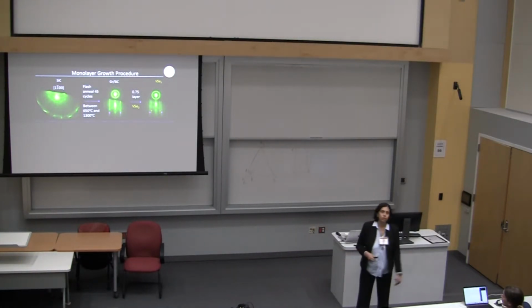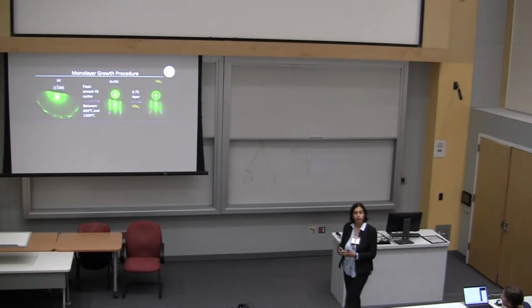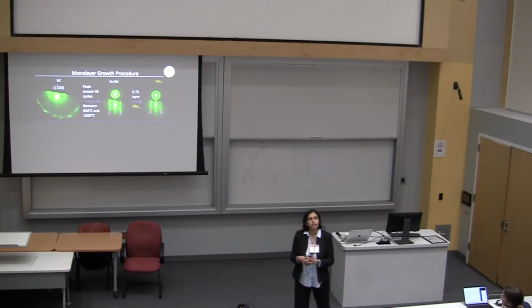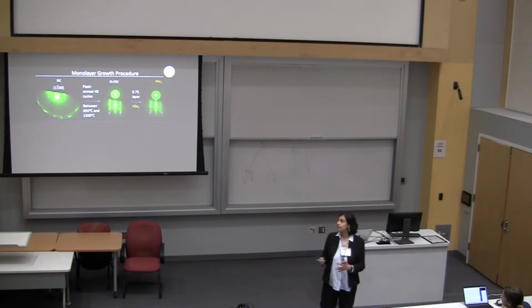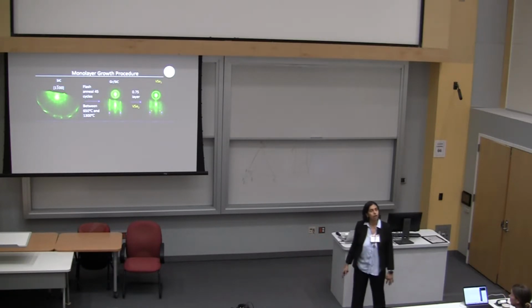So let me tell you what we do. A lot of the materials that we've been growing recently have been grown on bilayer graphene. And what we do is we take silicon carbide and we flash anneal it many, many times at high temperatures to make graphene on top.